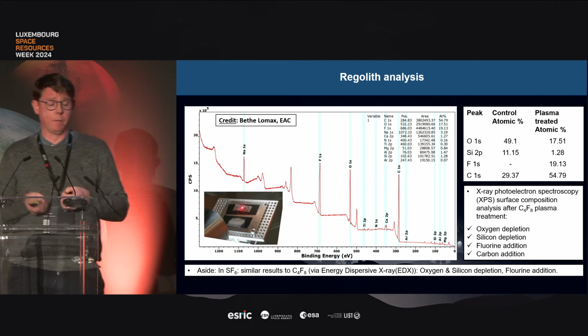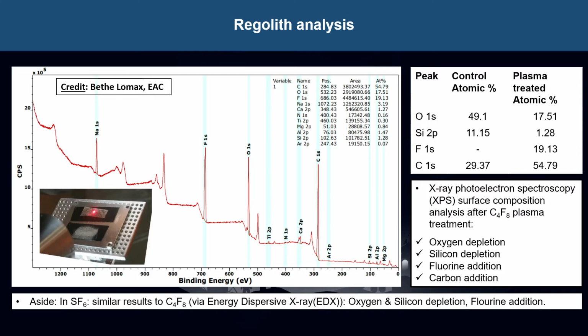So we've also been able to do very preliminary surface analysis of the regolith to get an idea of changes in its composition. This was carried out by Beth Lomax, I think at ESRIC, not EAC. So she did some XPS spectroscopy to look at the surface composition after C4F8 plasma, the fluorocarbon plasma treatment. And what we're seeing generally is that the oxygen is being depleted as expected. The silicon is also depleted, and that's because it's a volatile. Fluorine and carbon are being added to the surface also. We've begun to do some surface analysis also at DCU for SF6 chemistry. We're seeing a similar trend, of course, without the carbon, because there's no carbon source.